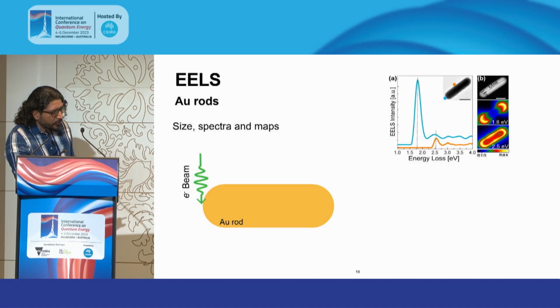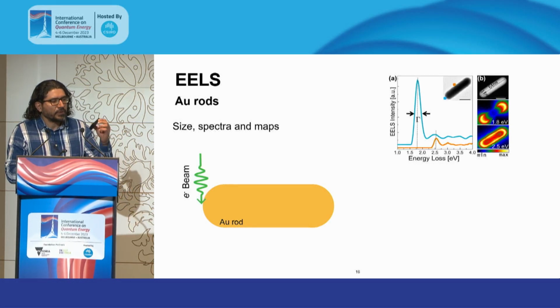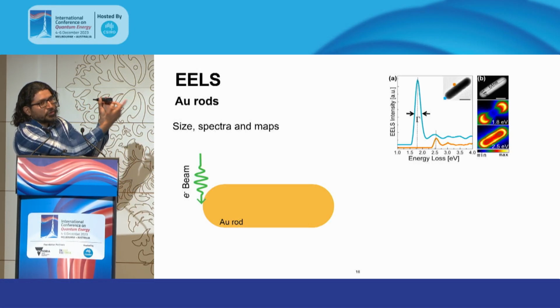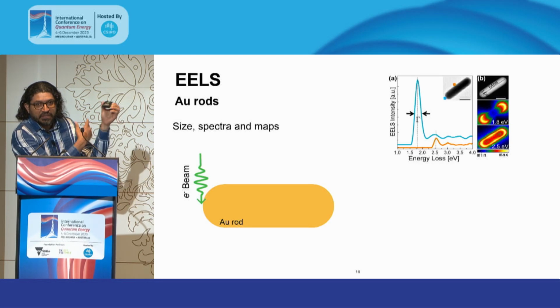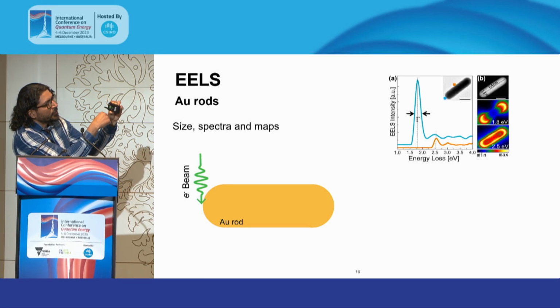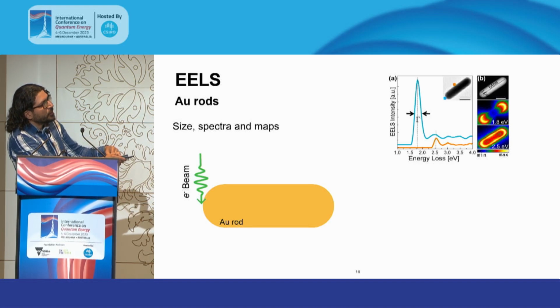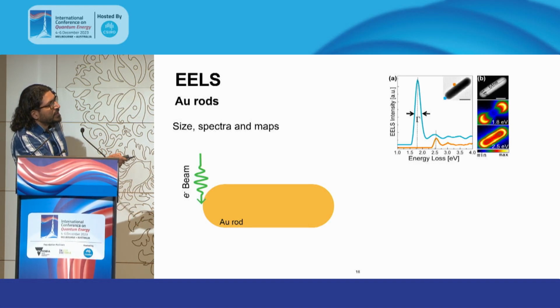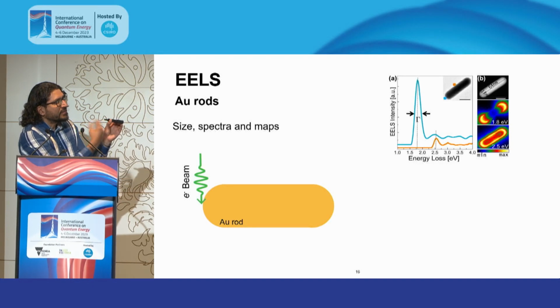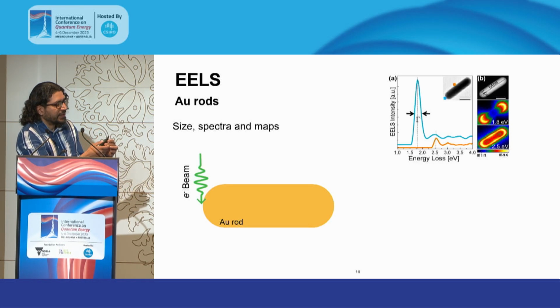So we start with a gold nanorod used to set up a control. With the electron beam, we get images. And as you can see here, the image has a strong intensity at the end of the rod. And that is because, if this is the rod, there is a longitudinal oscillation of surface density. This is the longitudinal plasmon band. The other one is the transverse plasmon band. And you can see that that corresponds to two peaks in energy loss, shown here at around 1.5 electron volts. An important thing there for us is the line width of the spectrum, because that tells us how fast that energy or oscillation is damped in the system.